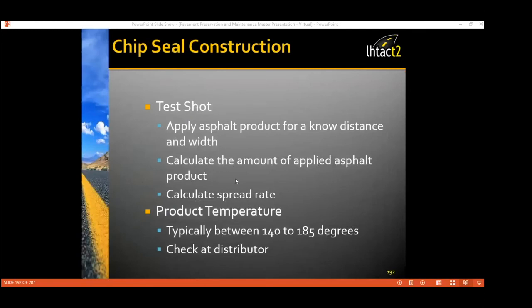So a test shot is desirable. You can apply the asphalt product for a known distance and width and then calculate the amount of applied asphalt product. And you can then calculate your spread rate. So you can really get a good idea of how much you're putting down. And again, the people who design this, or if you're contracting this out and you come up with a spread rate, don't be afraid to play with that spread rate if you need to in order to get your chips embedded to that nice 70%.